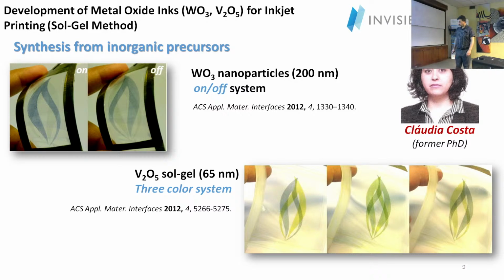So, we began earlier than this, but a breakthrough within our research in this area was achieved by Claudia Costa in 2012 while she was doing her PhD. So Claudia worked out ways to make metal oxide nanoparticles of tungsten and vanadium, and these nanoparticles could be deposited in PET plastic ITO electrodes, and so we built up these electrochromic devices that were published in 2012. And here are two examples with nanoparticles of sizes 200 nanometers and 65 nanometers.